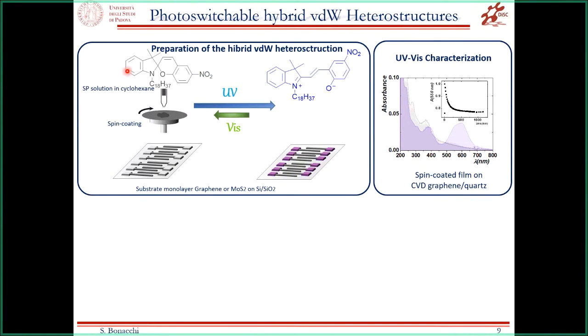So we spin coat spiropyran on top of a graphene layer, or also a molybdenum disulfide layer. And first of all, we observe if it's still possible to photoswitch this spiropyran molecule in the dry state, and it's indeed possible, as you can see here. We were able to photoswitch the spiropyran on top of graphene from the closed form to the zwitterionic form, and go back, and further for different cycles. So this was for sure one of our first achievements, the possibility to still induce photoswitching of this molecule even if we are working on a dry system, and if these molecules are on top of 2D flakes.